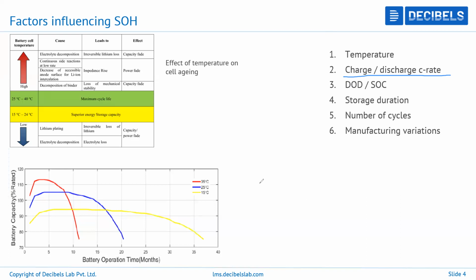So we know that if you supply extremely high current during charging, then your batteries can heat up, right? Which is why they restrict the charge rate of the cells, usually to 1C or less than 1C. Usually it is something like 0.67C to around 0.71C. So this is to maintain nominal operation of the battery, right?